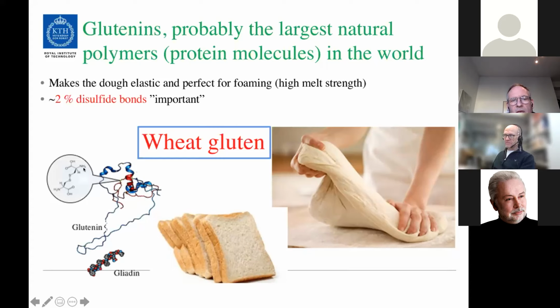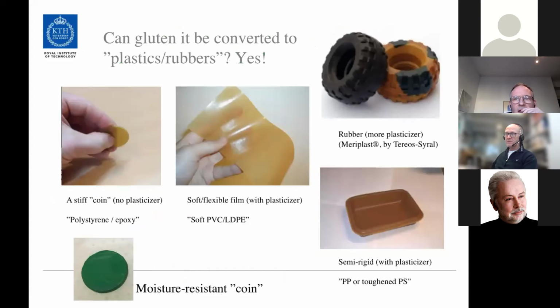What is important with these materials is that they normally contain cross-links. Disulfide crosslinks, and those are usually intramolecular from the beginning, but they can form between molecules when you, for example, knead a dough, and that gives you a stronger and stronger network, almost like a thermoset if you treat it at high temperature, for example. Here are some examples on what one can make from, in this case, wheat gluten.